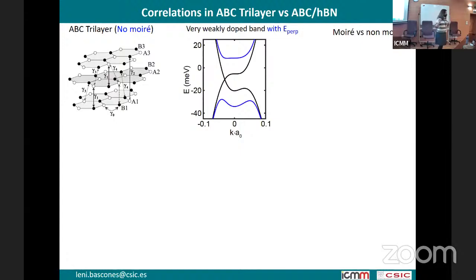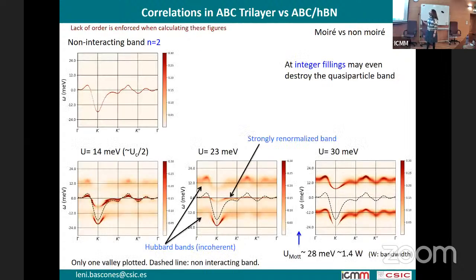So the question is, what does this mean? What is all this telling us as compared to the experiments? Before, the discussion was, okay, in this trilayer, when there was no moiré, they were finding ferromagnetic states. And they say, okay, this is just a shift of the bands. So if one increases U in this system, at some point you find a ferromagnetic transition. What I have said is that in our case, at integer filling, if we increase U, the band is strongly modified, even without any kind of symmetry breaking, even up to the point that it disappears.